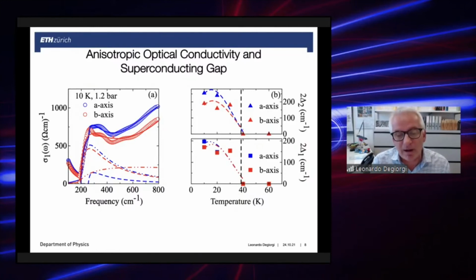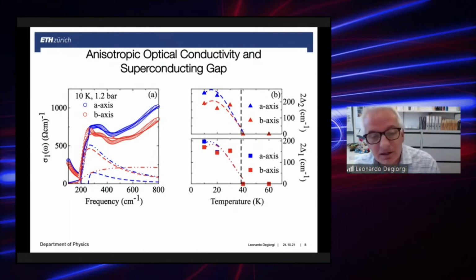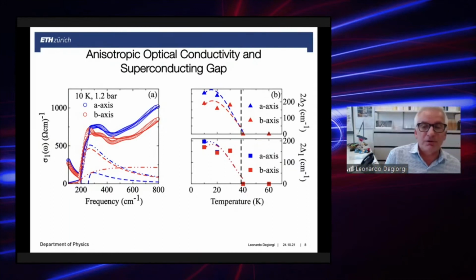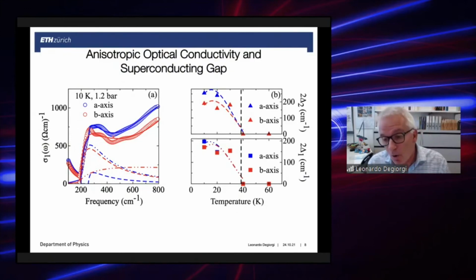but I'm not aware of measurement done in the same condition of this quantity. Actually, what I believe is that this behavior could originate from an anisotropy in the scattering rate, first of all, of the itinerant charge carriers. So driven by spin fluctuations, which turns out to be anisotropic in the nematic phase itself, in the stress-induced orthorhombic phase. And therefore, that nematic phase could be somehow vestigial of some kind of stripe magnetism. Or the other possibility, because of the anisotropy in the spectral weight, there are in optics two quantities, the scattering rate, but also the effective mass.